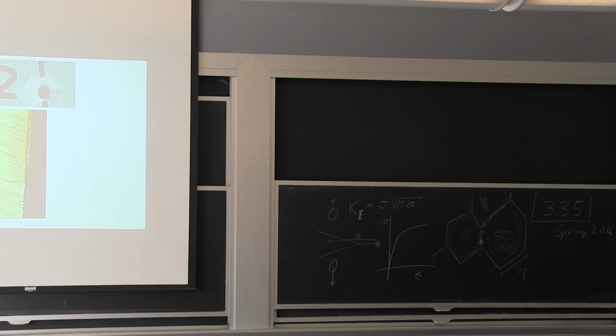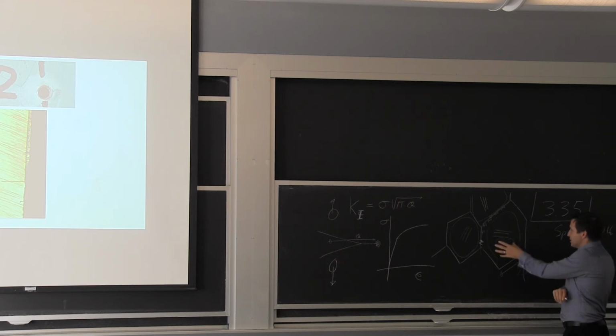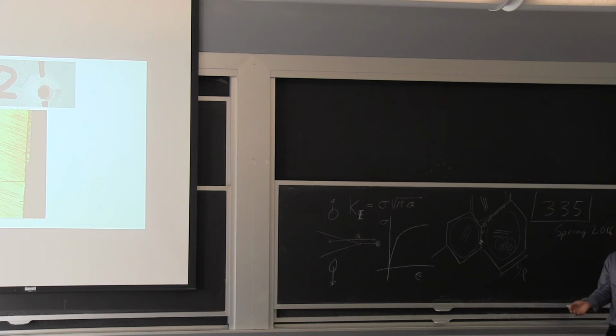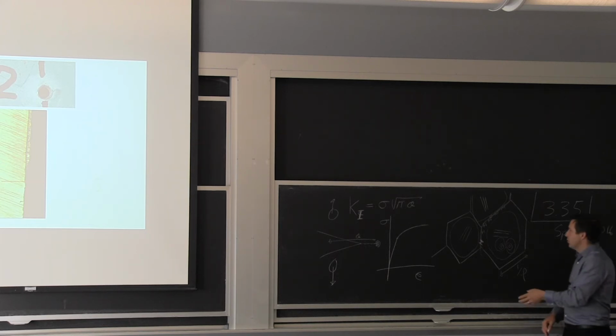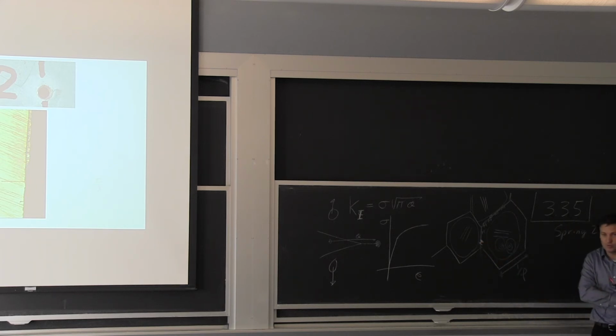I think what I want you to keep in mind is all of this is typically there. There's always a little bit of hydrogen, and there's always dislocation in the grains. And the question is, when are you reaching the critical point where you're going to go from one process to the other to create the fracture and all of a sudden lose, say, a factor of 10 in fracture toughness? And well, that's where you need a little bit more details, essentially.